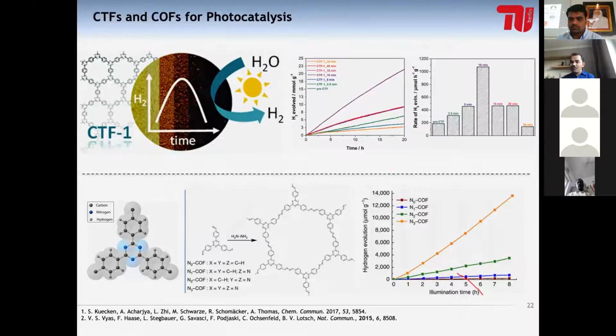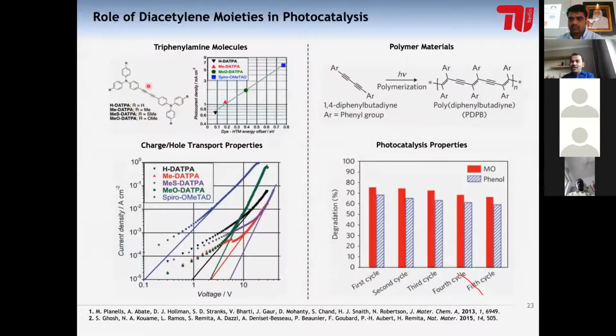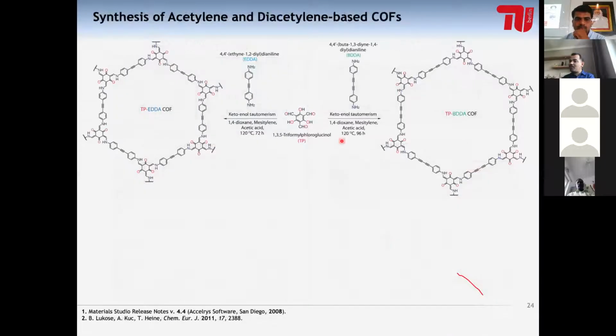But while starting to work, what I found was we can incorporate diacetylene moieties, which have good applications in hole or charge transfer properties, or some photocatalysis properties such as dye degradation. So a small moiety, the diacetylene moiety, can make a lot of changes in the structure and properties of the materials, showing really, really good photocatalysis. But is it possible to incorporate such targeted moieties into covalent organic frameworks to do photocatalysis? This was the target we took, and then we started thinking about how we can do that.